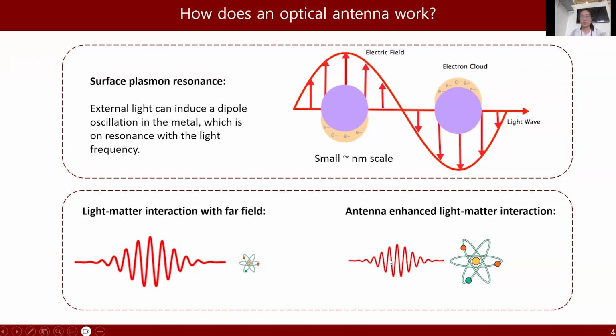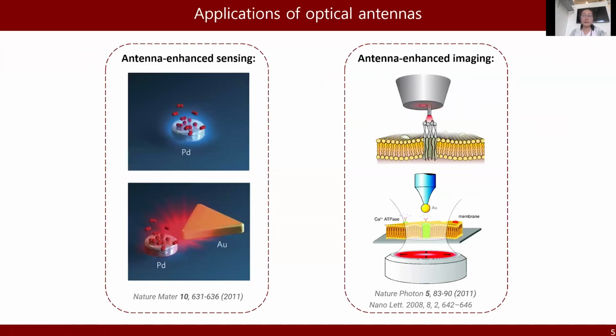But now if we consider there's an optical antenna which can control and concentrate the light at nanoscale, the interaction will be strongly enhanced. And because of that, optical antennas were used in many applications. For example, people have been using gold optical antenna to enhance the sensing of hydrogen concentration on palladium nanoparticle. People have also been using metallic tips as optical antenna to enhance the incoming laser and do scanning probe microscopy. And this imaging technique can also overcome the diffraction limit.